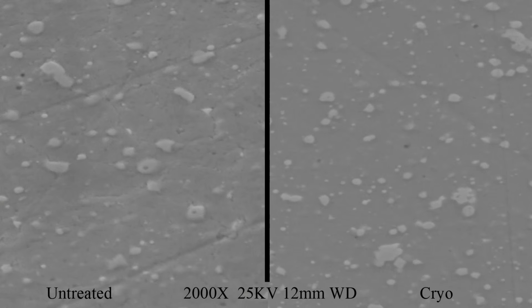difference. Again, I thought the difference was so shocking that something might have gone wrong. And so if you look carefully, you can see there's these grain structures pretty well defined in the untreated bit. And then in the treated bit, it's completely flat. Like there's no surface features that look like grain boundaries. The white dots are very likely carbide precipitates.